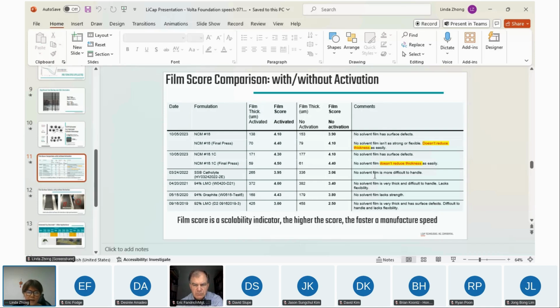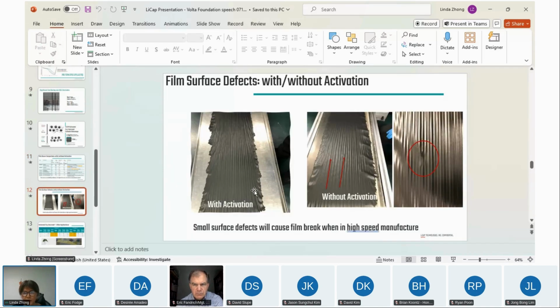Now, if you compare the freestanding film made with activation and without the activation, this is almost the best scenario when you look at the film without the activation. If you look by naked eye, they look almost the same, and you don't see much problem. But if you look under the microscope, you will see the defects. Those surface defects are the reason you cannot run them fast, because those are the weak points, high stress concentration areas. So when you run the film with speed, they start to break.